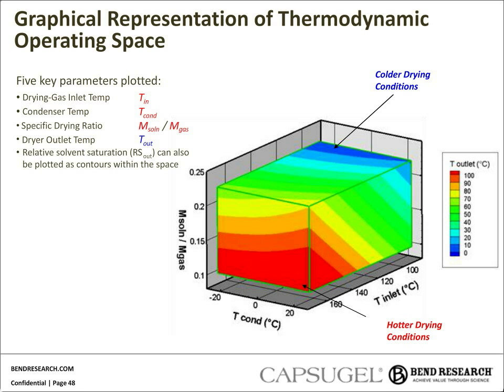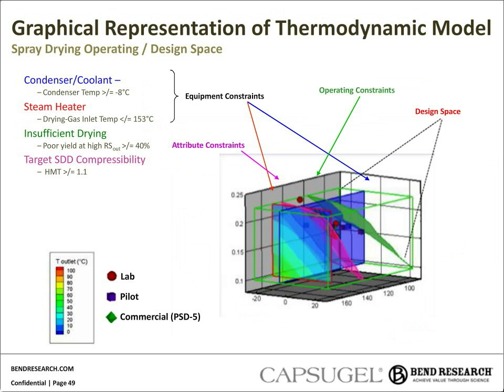We can also plot contours of constant relative saturation within the space. So in this type of 3D box, the colder, wetter spray drying conditions are shown towards the back left-hand side, and the hotter, drier conditions are shown towards the front corner. So again, similar to the thermodynamic operating space we reviewed in 2 dimensions earlier without the condenser temperature, we can lay out or map out an operating space. We've plotted the experimental conditions for a 25% HPMCAS SDD at PSD1, PSD2, and PSD5 scales within this three-dimensional operating